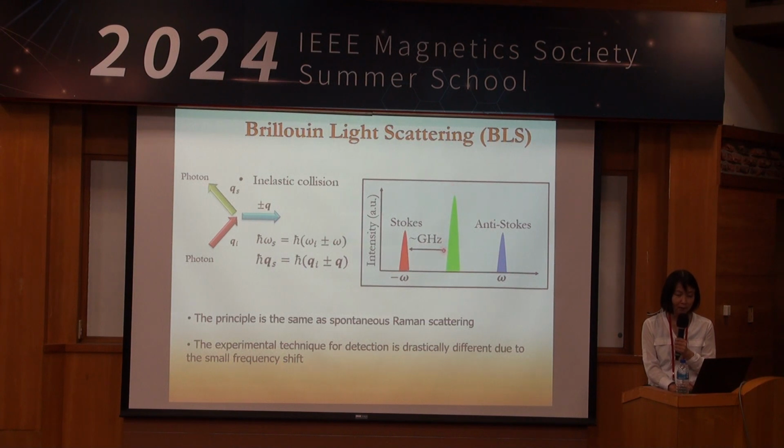So this is the incident laser. If you absorb a phonon or magnon, you end up with an anti-Stokes peak, where the frequency of the outgoing photon goes higher. But many times the Stokes peak is stronger, especially when the frequency gets larger. In that process, the photon actually loses energy because it's creating a magnon or a phonon. A Raman spectrometer is basically based on a grating, and you just shine light on it. You separate the Rayleigh scattering, which is the photons that have not interacted with the matter wave, from the Stokes and anti-Stokes peaks, which have a very small percentage efficiency.